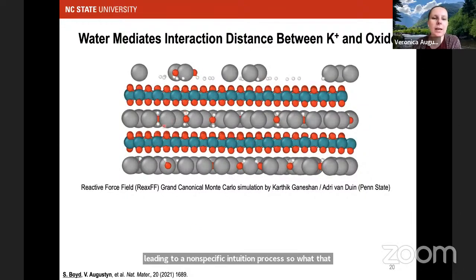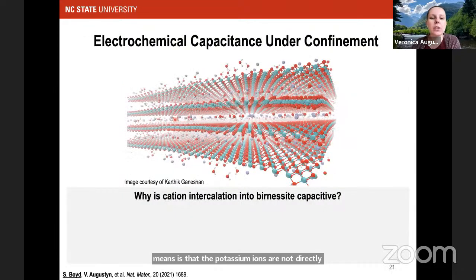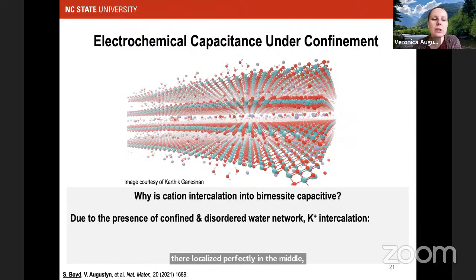So what that means is that the potassium cations are not directly bonding to any particular site within the interlayer. They're localized perfectly in the middle. And that's why the cation insertion is capacitive. It's really due to the presence of that confined and disordered water network, so that the potassium insertion occurs right in the middle of the hydrated interlayer. There's even some partial solvation of that potassium by about 3 water molecules that surround it. It's non-specific, so the potassium is in the middle and distributes randomly. And most importantly, since it leads to very little structural change in the electrode, the water that replaces the potassium keeps layers from rearranging. And we think that's an important component of why this gives rise to very high cycling stability for this class of materials.